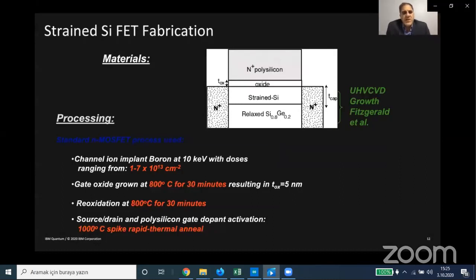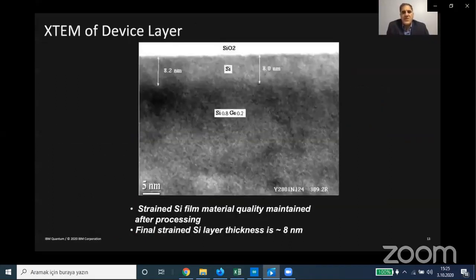transistors in the clean room, looking at, first of all, high doping in the channel to control short channel effects and achieve the threshold voltage required. We also had to develop a low temperature process to prevent relaxation of the strain layer at the top and mixing between the two layers. This is a TEM of the final device structure.